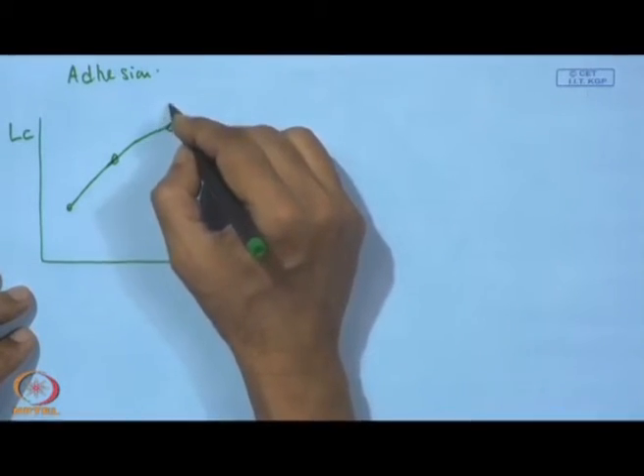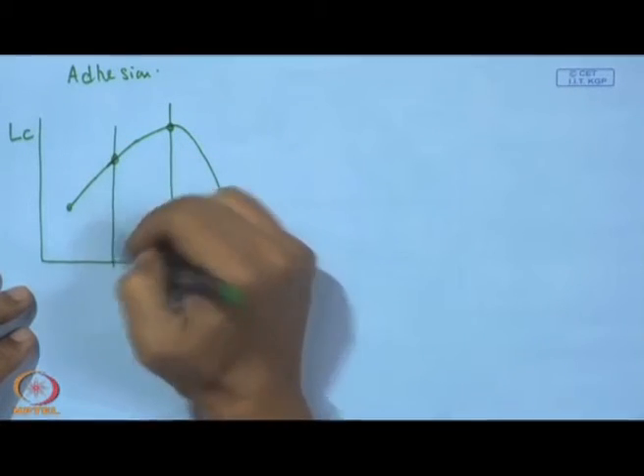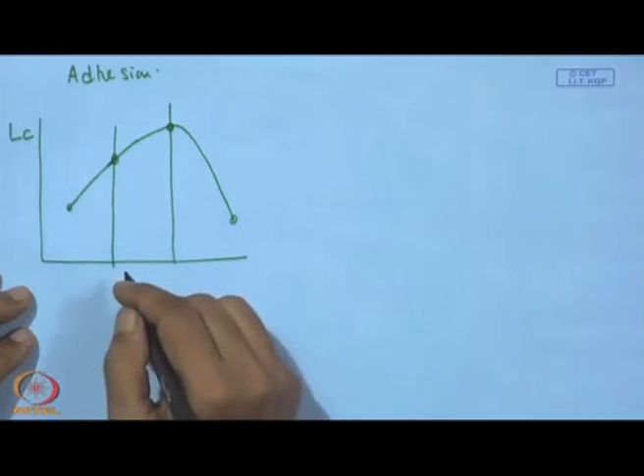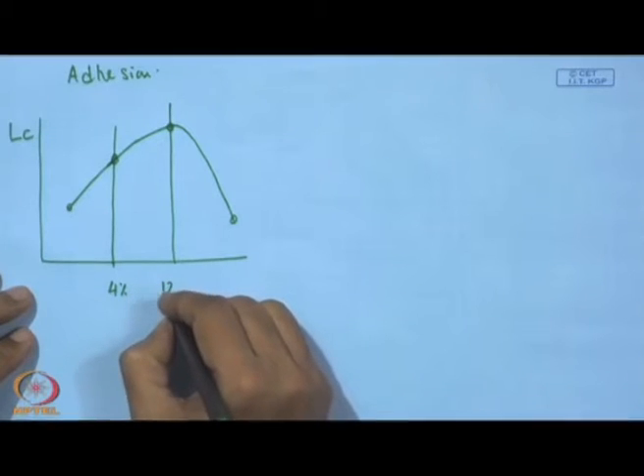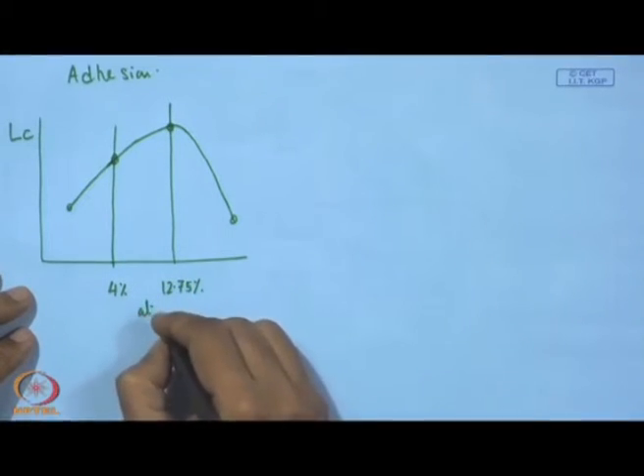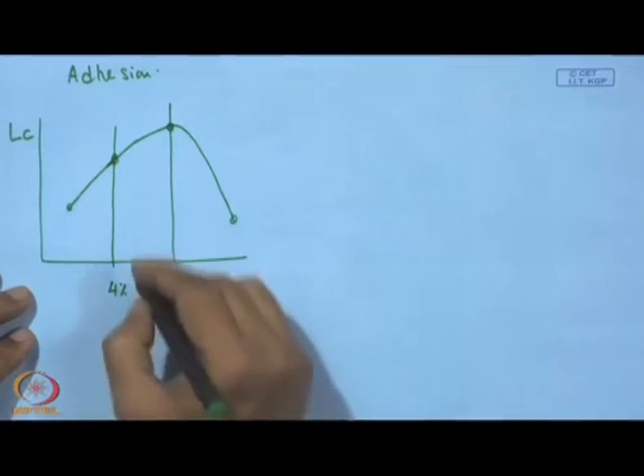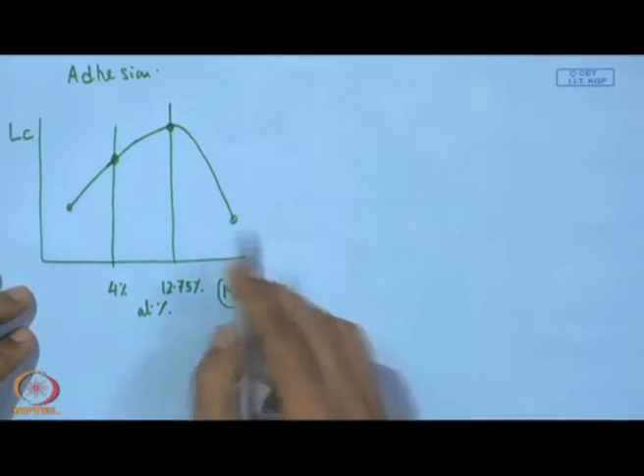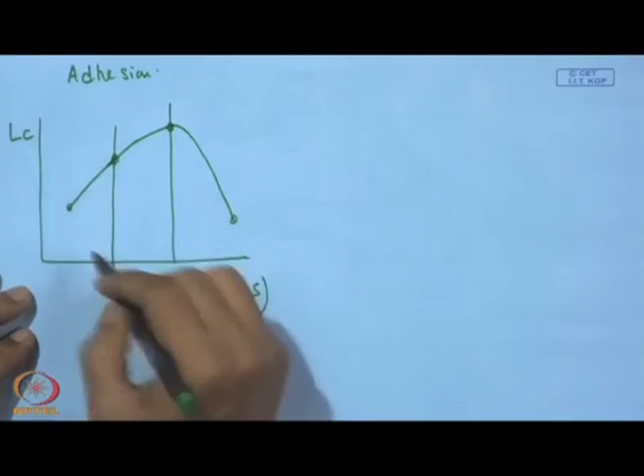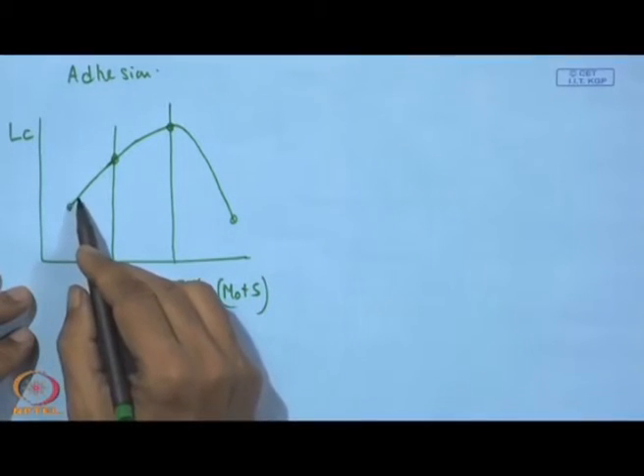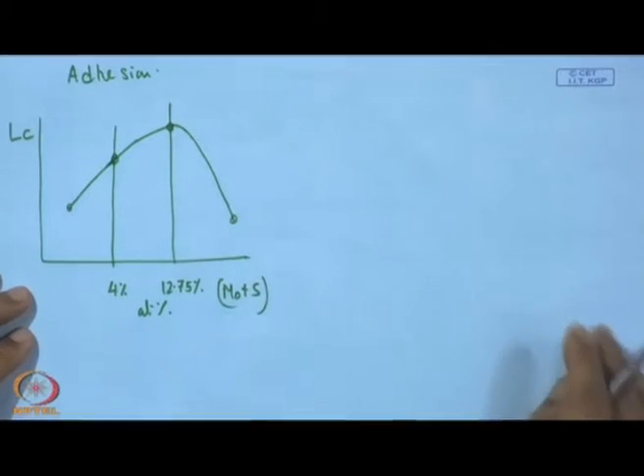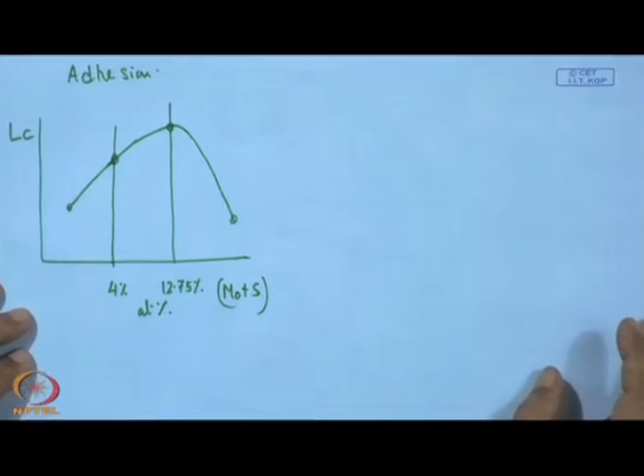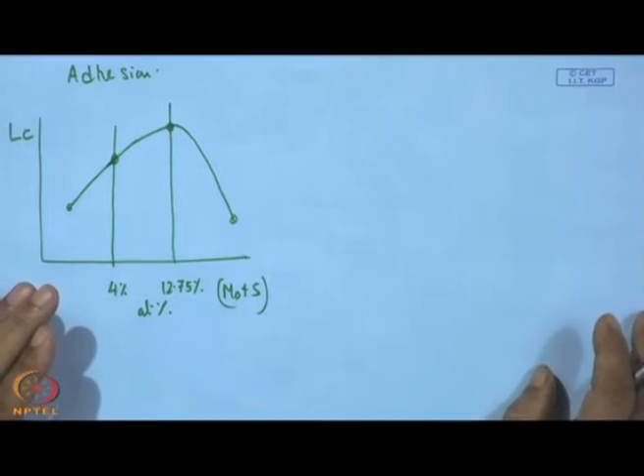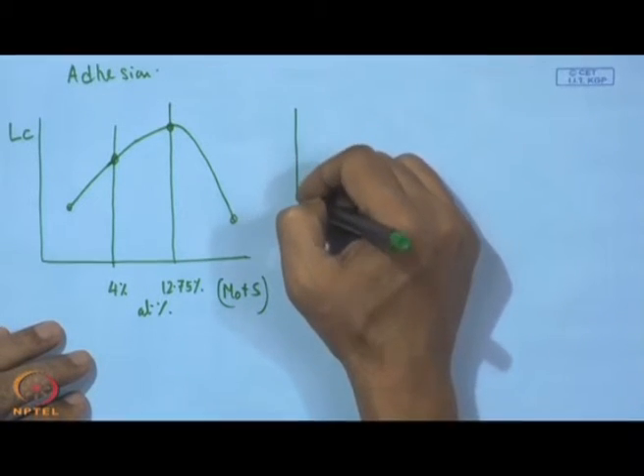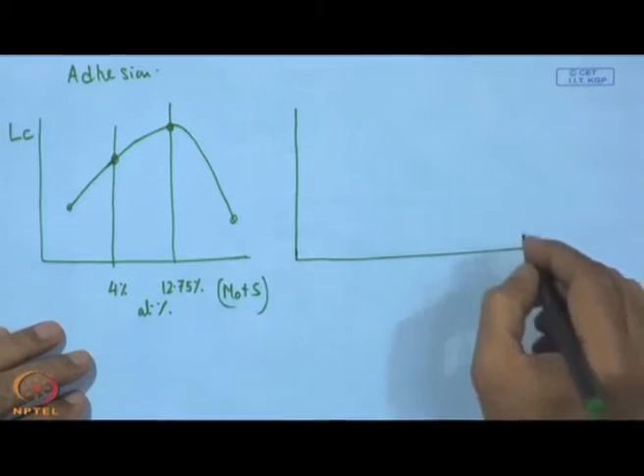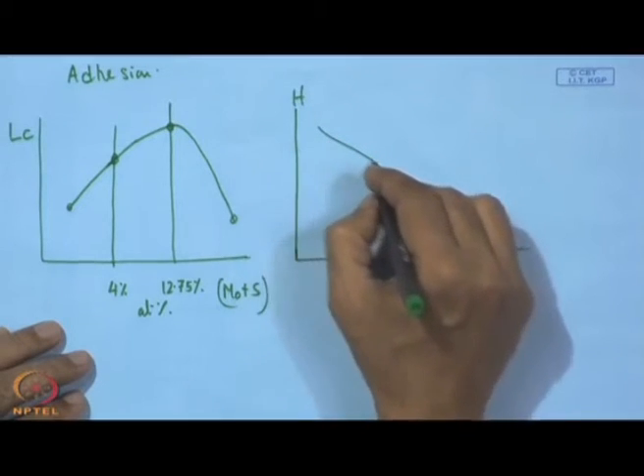So, this is actually a zone where we have a good result. That means the good result is somewhere around 4 to 12.75 atomic percent of Mo plus S, where we can get a good value of LC, that means the adhesion. But when it is below that, it was dropping sharply, and here also it has a very sharp fall. So, this can be considered a zone where it is expected to give a good result. However, hardness wise it is continuously falling.